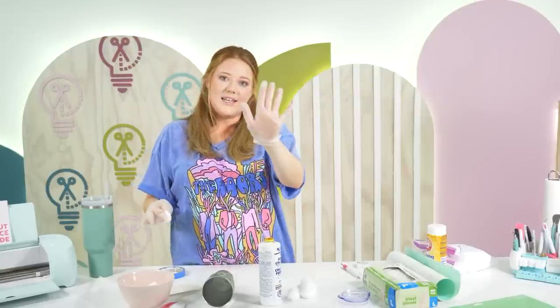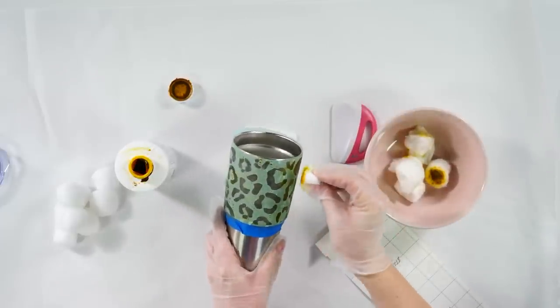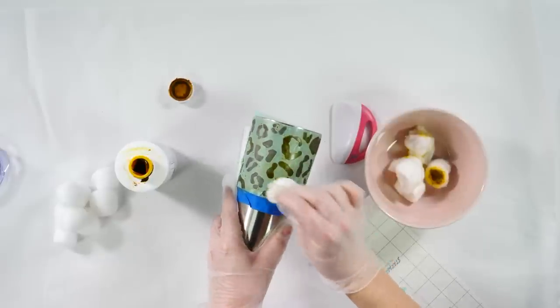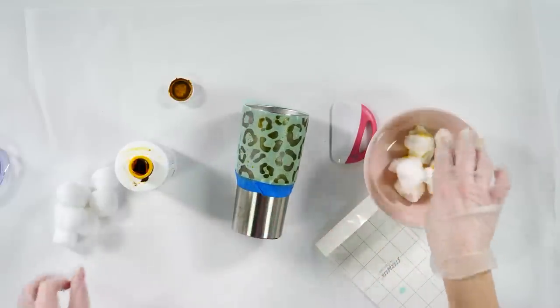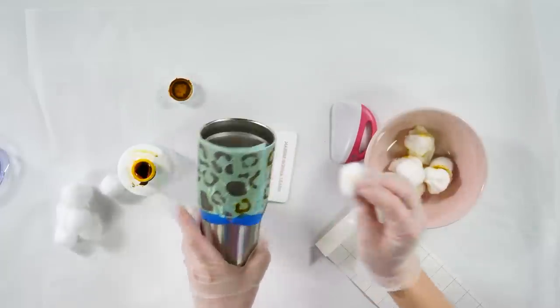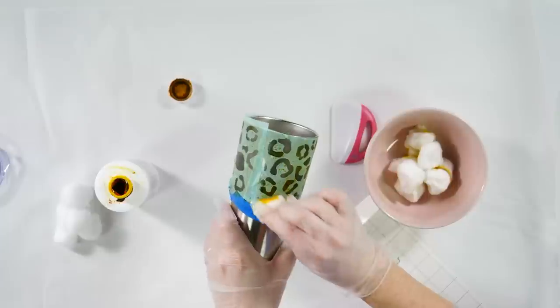This acid is not just for stainless steel — you can use it on copper, brass, and other materials. I'm going to go rinse this off in the sink and then we'll reveal it together. Before I go — I'm going to put baking soda on the cup to neutralize the ferric chloride. I'm also going to put it in this bowl to neutralize any ferric chloride on the cotton balls. I'm also going to add water before I throw these away. Why? Because this is an acid and it's corrosive — it'll eat through whatever's in your trash can. Neutralize it with baking soda and then water.